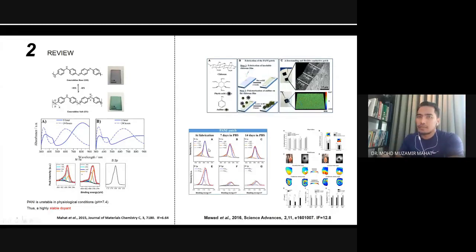So look at this figure. This is an XPS data. In my lecture for advanced materials characterization, I will explain it further for you. But what I show you today is that we managed to see a huge improvement in terms of the stability of the polymer. You can see that this is the phosphorus. This is phosphorus. This is phosphorus. Phosphorus is the element that we wish to be there